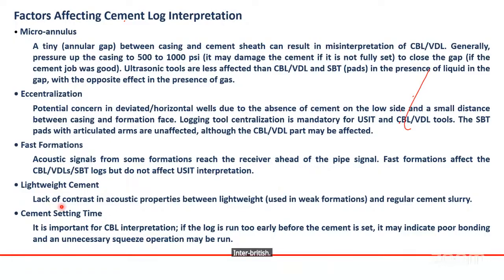Lightweight cement: lack of contrast in acoustic properties between lightweight cement used in weak formation and regular cement slurry. Cement setting time. This is an important one because the drillers usually try to accelerate the non-drilling time. So they say, okay, the cement will be set in 40 hours, 48 hours, and so on. But it's important for CBL interpretation. If the log is run too early before the cement is set, it may indicate poor bond and an unnecessary squeeze operation may be run.